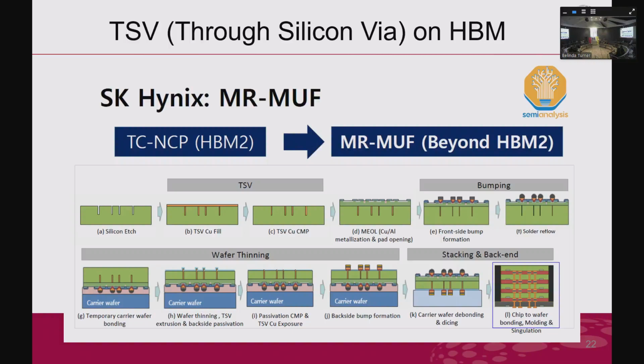Okay, so first silicon etching. I think I talked about this in the previous slide. We rely on chemical and physical reaction to form that deep trench or deep groove. Then we fill it with copper because copper is the main conductive material used. There is also a lot of research here because when you fill in the copper, you need to make sure of the uniformity. That means when you create a highway, you need to put down good paving, right? Then the electrons can move smoothly and quickly without loss. Then you do CMP, the polishing process. It's a mix of chemical and mechanical polishing. You polish the copper, and then you start to form bumping.